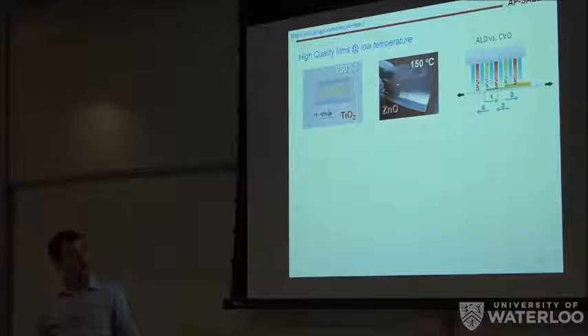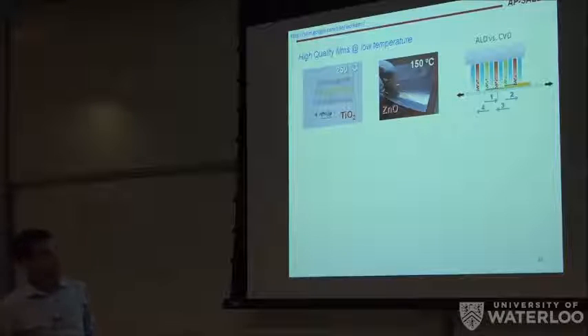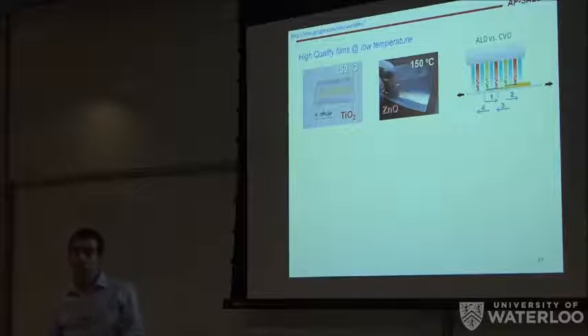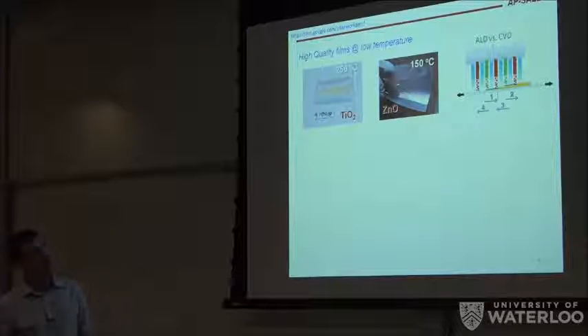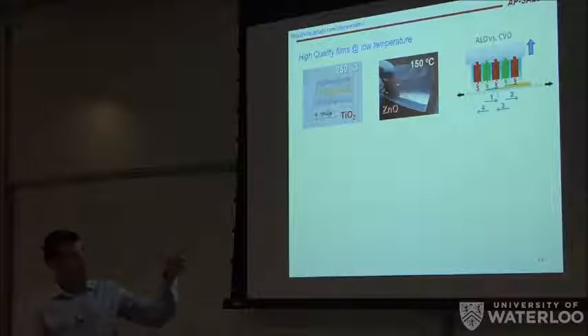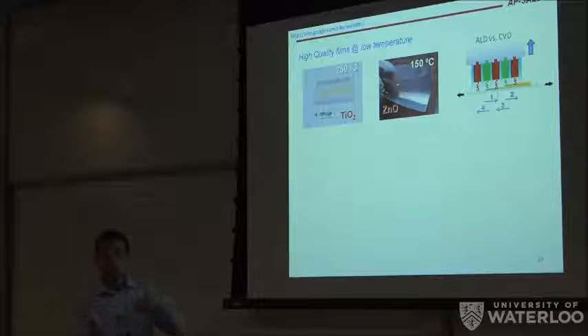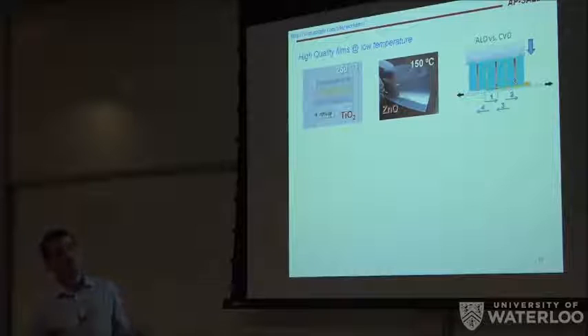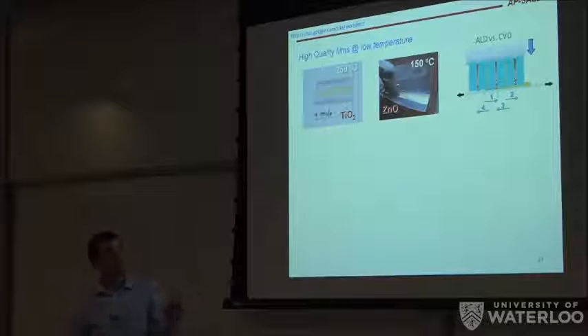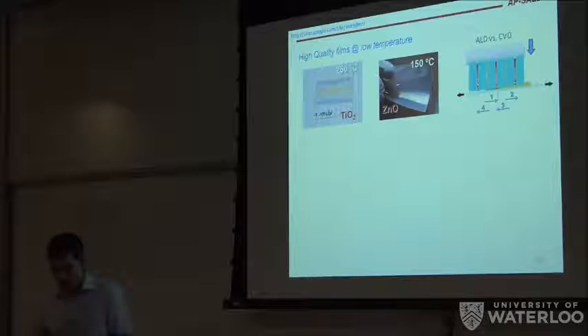And the good thing about this close proximity approach, as it is called, because as I say, we need to have the substrate close to the head, is that we can switch between more strict ALD conditions, but also CVD, because we can tune the flow through the metallic precursor channels, and we can play with the gap. If we increase the precursor flow and get a bit away from the substrate, we allow certain mixing of the precursors, and then we're going to have some CVD growth. On the other hand, if we get closer and we increase the nitrogen flow, we are favoring more strict ALD, so only surface-limited reaction.